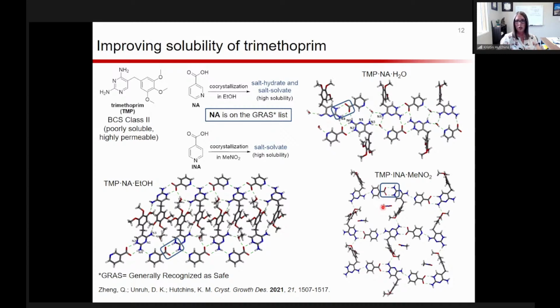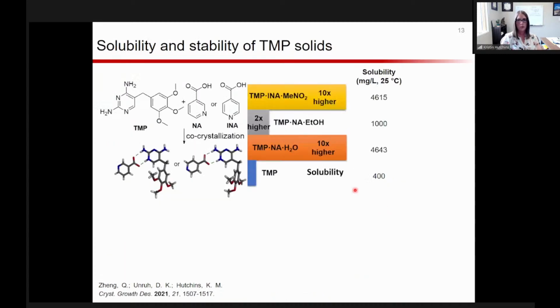And so we decided to look at the solubility because it was really our goal to improve that aqueous solubility. In all three cases, we actually did increase the solubility when compared to trimethoprim by itself. So trimethoprim here at the bottom. And really what we were excited about is that nicotinic acid water salt actually had a 10 times higher aqueous solubility when compared to trimethoprim. The nitromethane solvate did as well. Nitromethane is not safe to give to humans, so this was not nearly as exciting as the case where we have nicotinic acid and water.